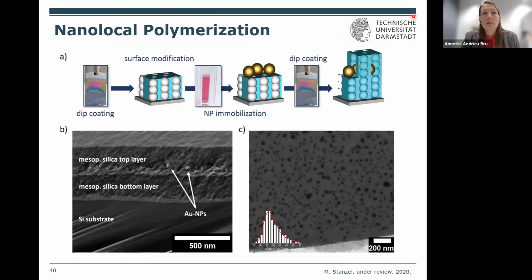Yeah, I mean, the question here is a little bit which plasmonic source you use. So the particles are one option. What we do here is basically this layer-wise deposition. So you have a mesoporous layer. You can tune the thickness of that layer. You can tune the porosity of that layer by using the template. Then we deposit the particles and deposit a second layer. So here you would have control in terms of the nanoparticle type you use and the thicknesses you adjust.